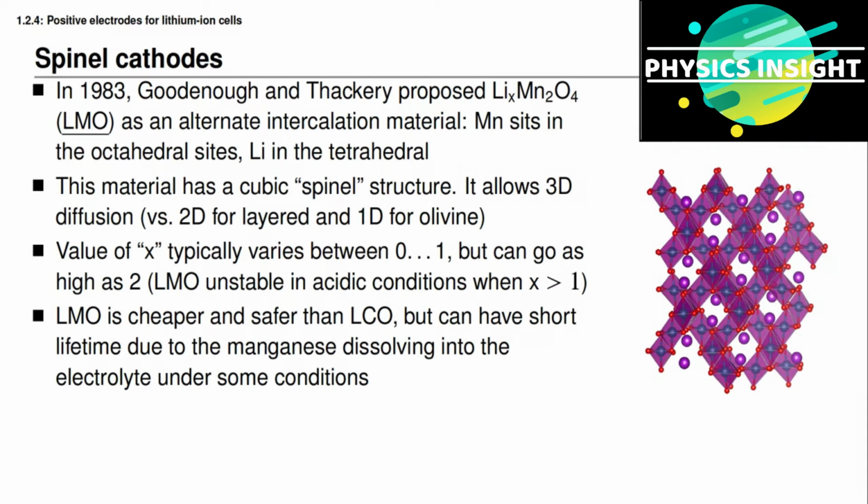And so the manganese can dissolve, and the positive electrode structure basically dissolves, and there are fewer vacancies that are able to hold lithium, and so we have capacity loss. So when we build the cell, we try to eliminate moisture, but it's not possible to eliminate it completely. We build the cell in an environment where the electrolyte is injected in what's called a dry room, where we've evacuated as much moisture as we reasonably can, but there will always be some moisture in the electrolyte.